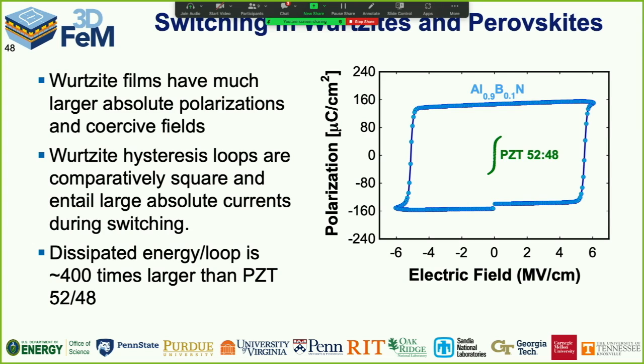But there's some things that are a little scary. That is the hysteresis loop of lead zirconate titanate compared to the hysteresis loop of aluminum boron nitride. That is open, but the coercive field is like 5 megavolts per centimeter. Recall that all the area in that loop is energy loss, which means every time I run this polarization loop, I'm dumping energy into the solid. That is something we're going to have to engineer out. I suspect that we will need to learn how to create nuclei which are chemically induced that basically facilitate the reorientation process at lower absolute electric fields. So we have work to do on dissipated energy.